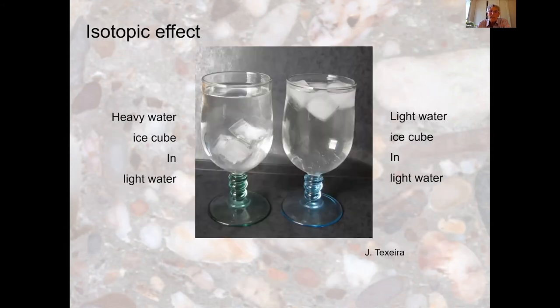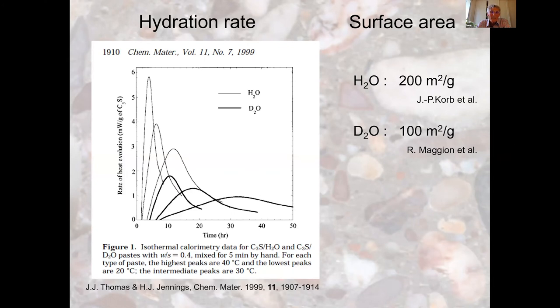Another point which I think is very questioning, and which is not far from what has been discussed during the conference, and which is not very well known, is that there is a very strong isotopic effect in the hydration of cement. As Thomas and Jennings showed more than 20 years ago, hydration of cement in D2O, in heavy water, is much, much slower than in light water.